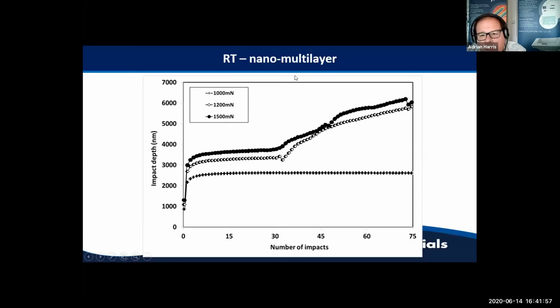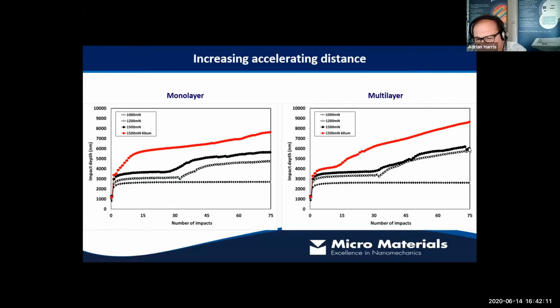The nano multi-layer gives an essentially similar response, but its final depths are just a little bit bigger. If we put them next to each other, you'll see that on average they're just a little bit deeper on the multi-layer sample than on the monolayer. Other than that, there's really not a whole lot to pick between them.